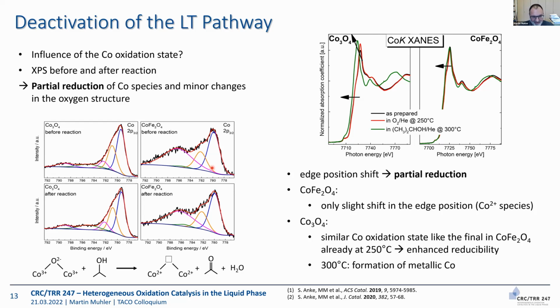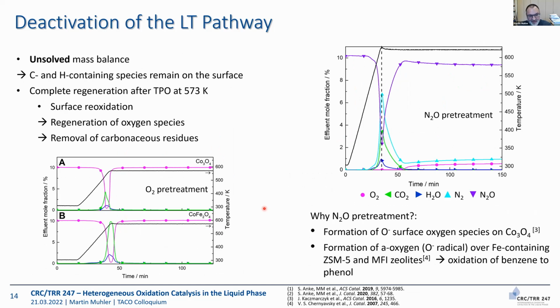That was very puzzling in the beginning. There are various options. One would be that we reduce the cobalt species too strongly. So we applied XPS, and these are Beatriz Roldán Cuenya's data. We checked, of course, when you go up to high temperatures and under strongly reducing conditions, then you can perform even a kind of bulk reduction. When you look at the XPS data before reaction, after reaction, you see there are not that many really pronounced changes. So there is some reduction, but that doesn't seem to be the main reason for this disappearance of the low temperature pathway.